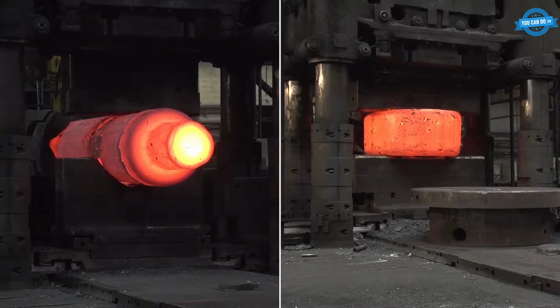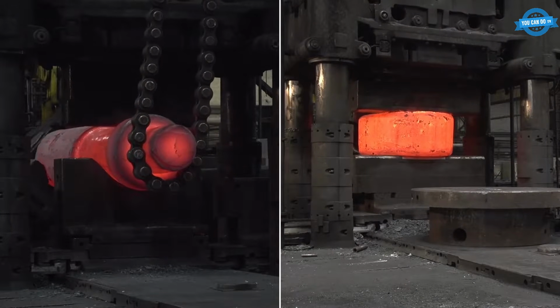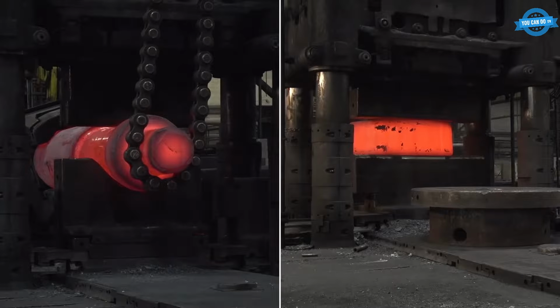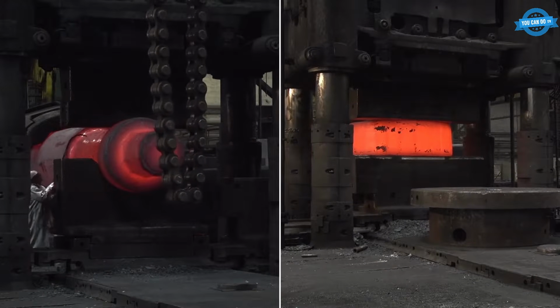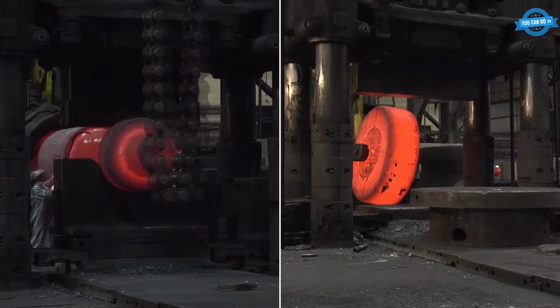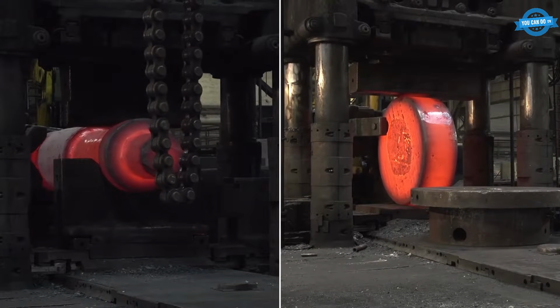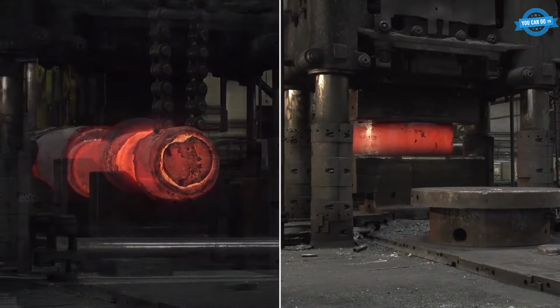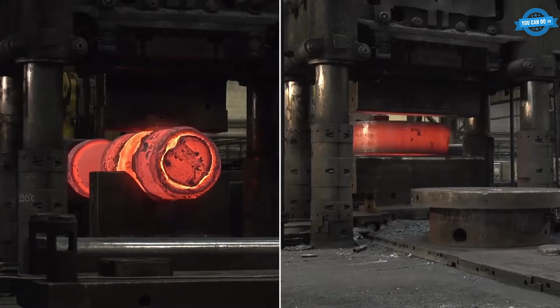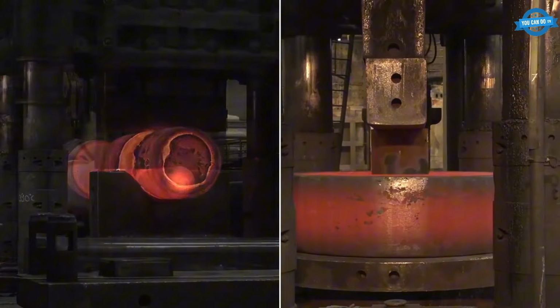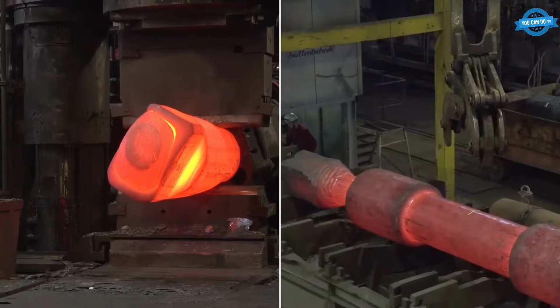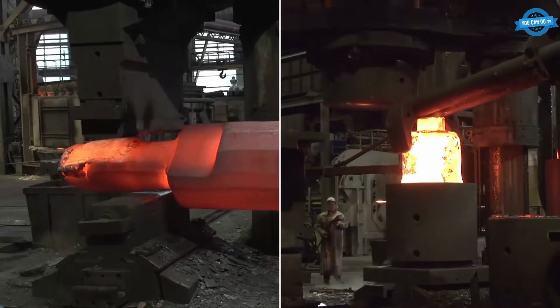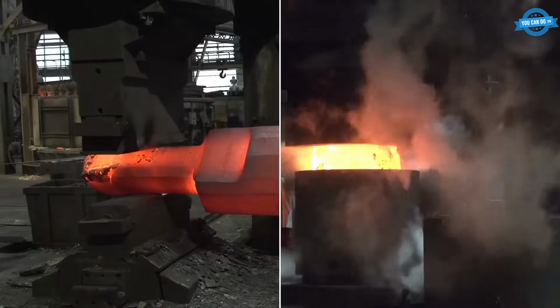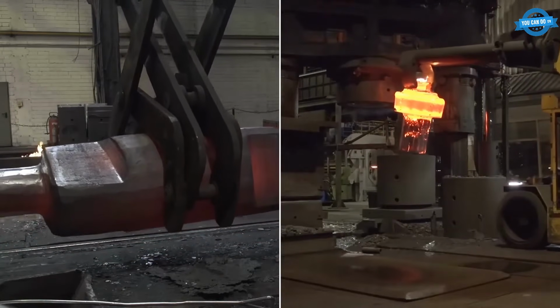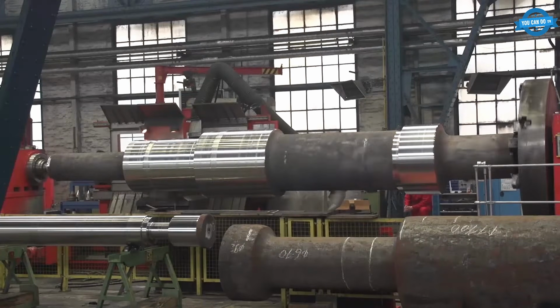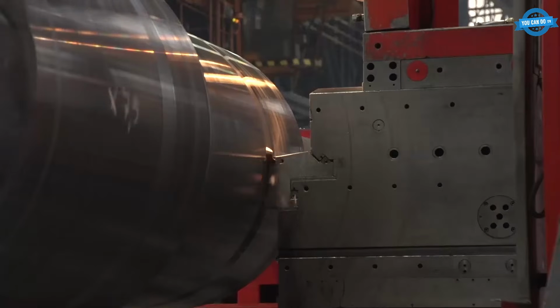Then it goes into the annealing furnace, up to 1,200 degrees Celsius, and lands on a 60 meganewton press. The manipulator grips the forged end, and the pre-forging plus upsetting cycle begins. Turbine shafts and turbine wheels take shape stroke by stroke. The real limit on the whole line is furnace throughput. The press can strike faster than the steel can reheat, so productivity comes down to how fast the surrounding equipment can keep up. You've got the world's meanest hammer waiting on a very slow toaster.